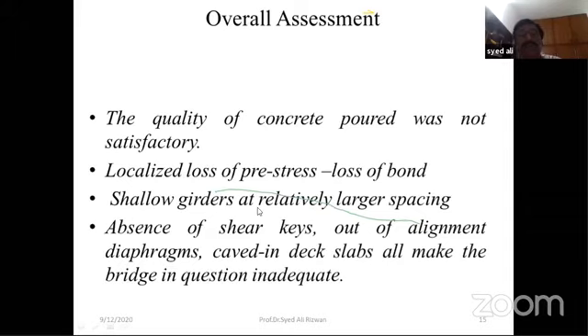The girders were relatively shallower and were placed at larger spacing. And there were no shear keys. Out of alignment diaphragms, caved in deck slabs, all made the bridge in question inadequate. But this resulted due to subletting of the contract to a lower category contractor. The main contractor ran away.